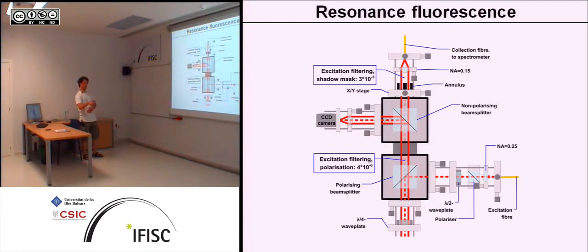So we come from the side for excitation. We collimate this beam with a very small diameter. Then we polarization filter it, rotate its polarization by 90 degrees, and basically let it propagate through the similar polarizing beam splitter as we have here. And that means, because of the 90 degrees rotation, it will be deflected downwards. If you now imagine down there the quantum dot sample, it will bounce up again, also the quantum dot photons,